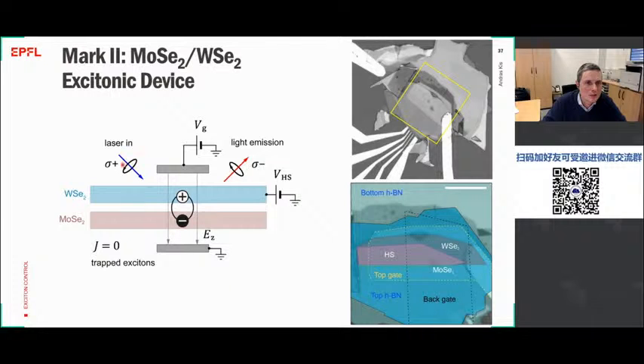And in this type of device, we could indeed observe polarization. And more interestingly, we could actually switch it using local electric gates. But what happened is that the excitons got trapped. The Moire potential in this combination of materials was so strong that the excitons could no longer freely diffuse. They were trapped in different regions of the Moire lattice. And I'm going to go to that point in a few slides.